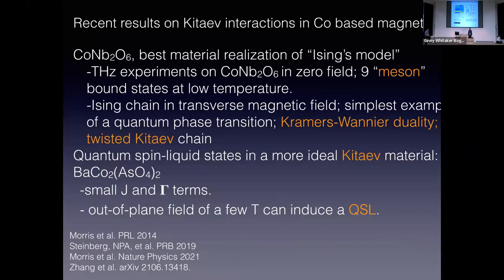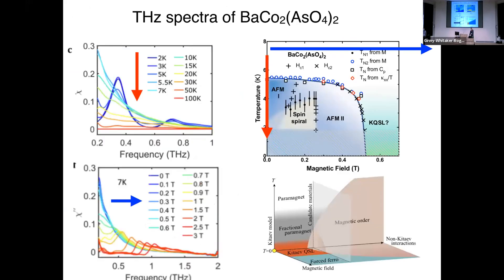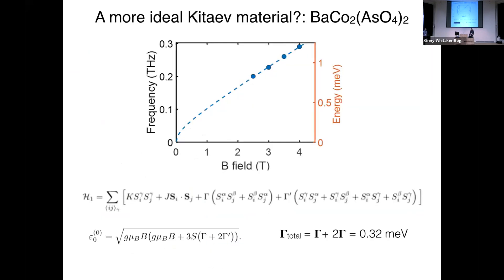That's all I'll say, but I'm happy to take questions. [Q: For the 2D material, what fraction of the Kitaev exchange is the estimated gamma?] So what we're sensitive to is a weighted sum of gamma and gamma-prime. In this system those numbers are something like 10% — we believe the gamma terms are of order 10% of the Kitaev exchange interaction. The number in alpha-RuCl3 is like about half. So the cobalt compound is both smaller in absolute magnitude and smaller as a percentage.